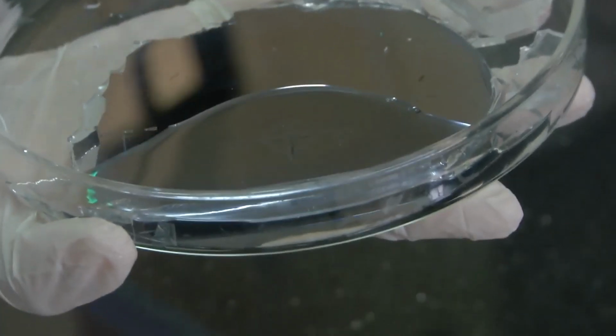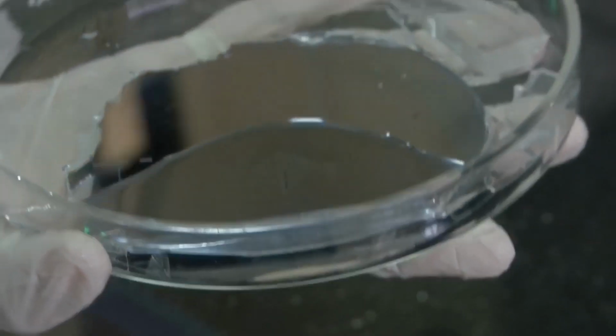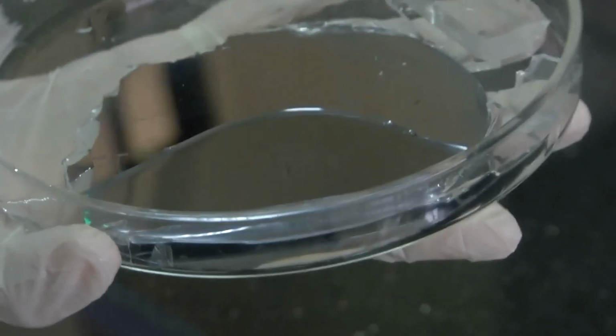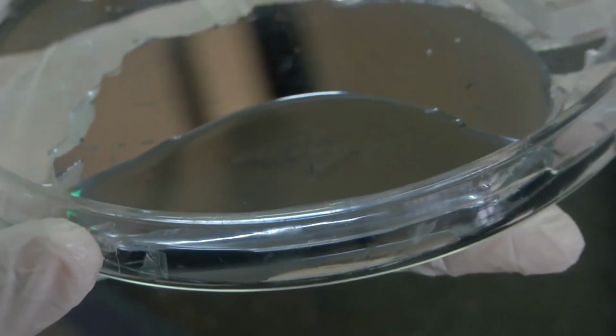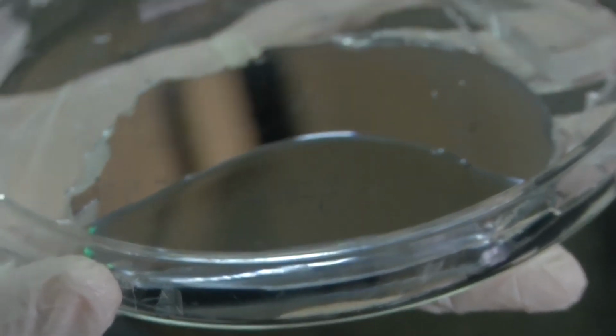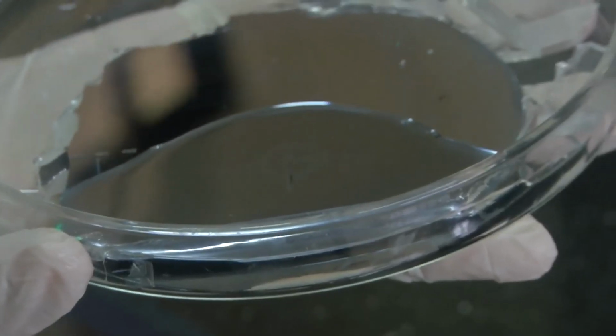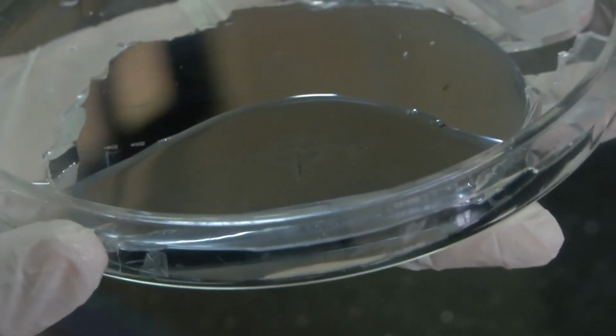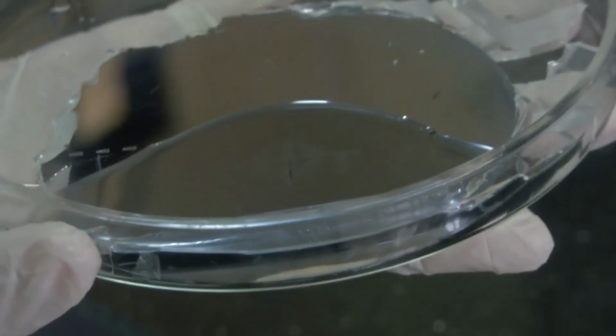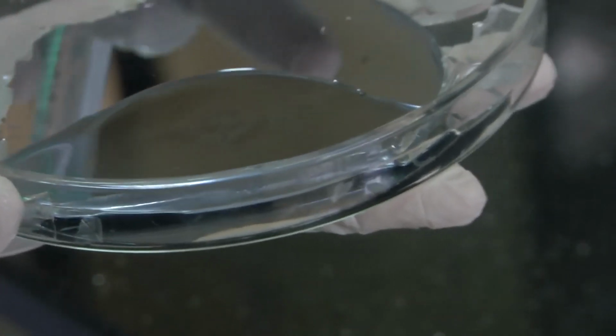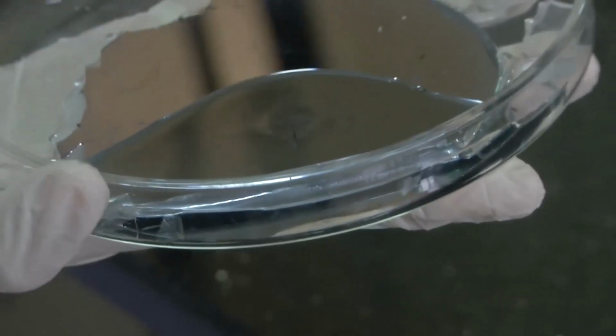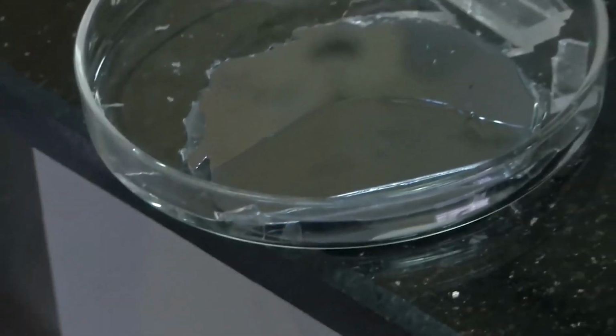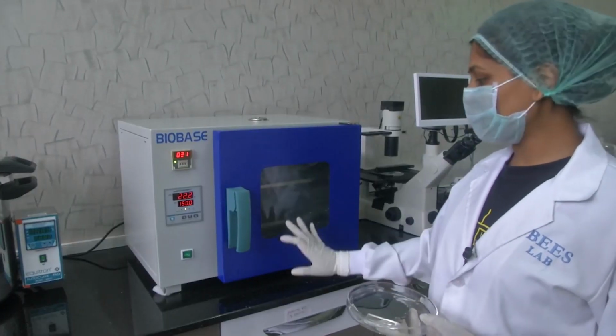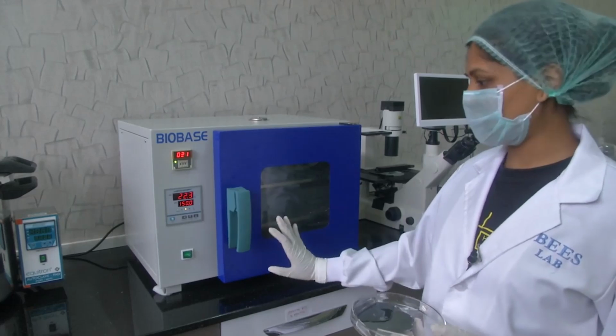Now that we have seen how the liquid goes into this, we have to cure this. The setting we have to follow is to put it in an oven at 70 degrees Celsius for 2 hours. What happens if you set it at a higher temperature? The curing at higher temperature makes the mixture brittle and the device tends to break. Hence, the optimum temperature is 70 degrees Celsius for 2 hours. So, set the oven temperature to around 70 degrees Celsius.